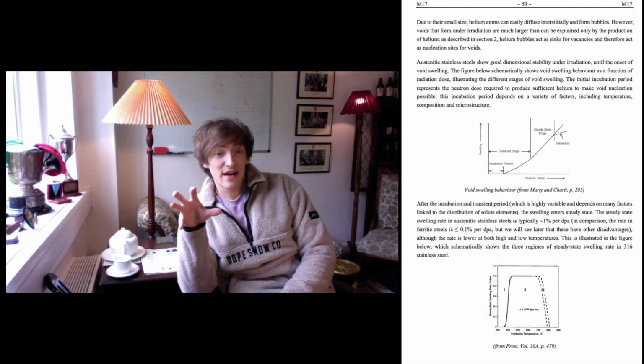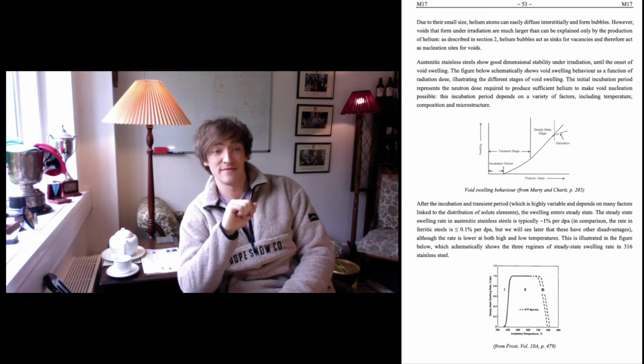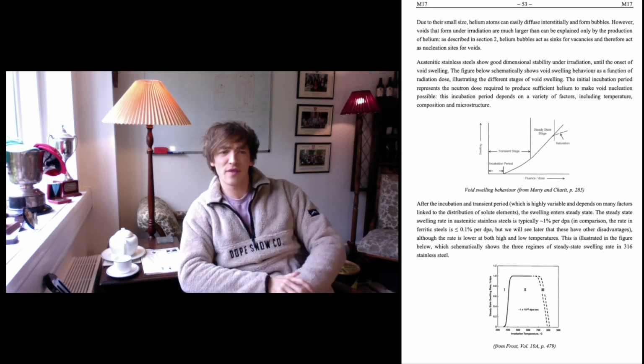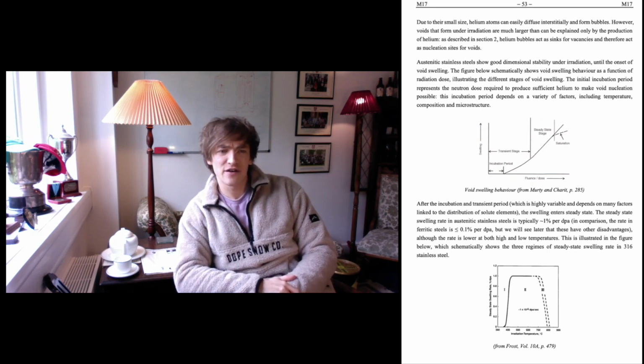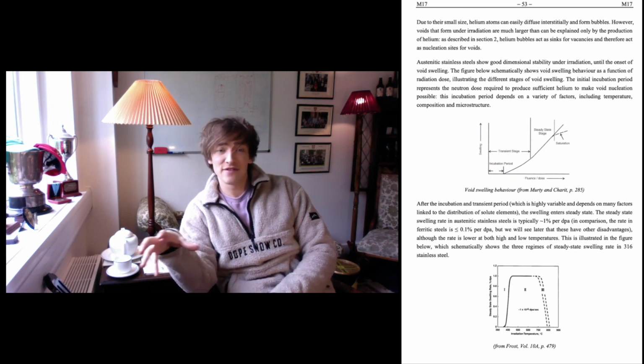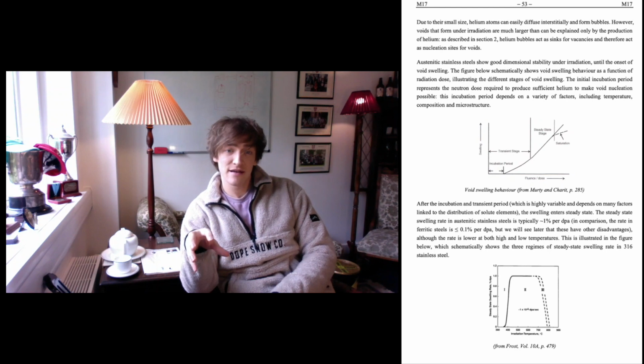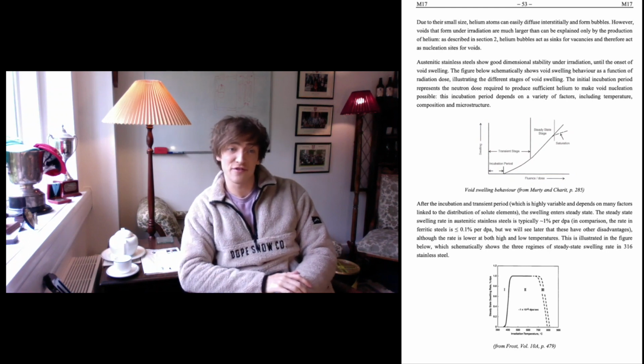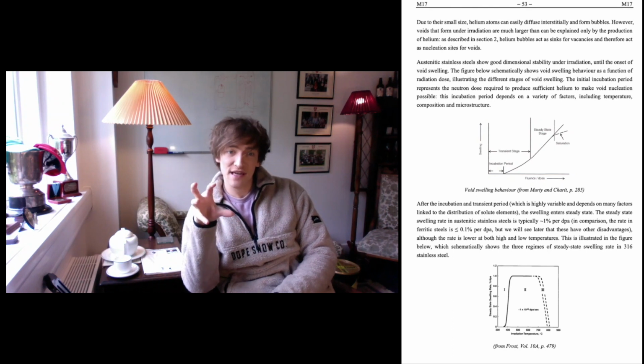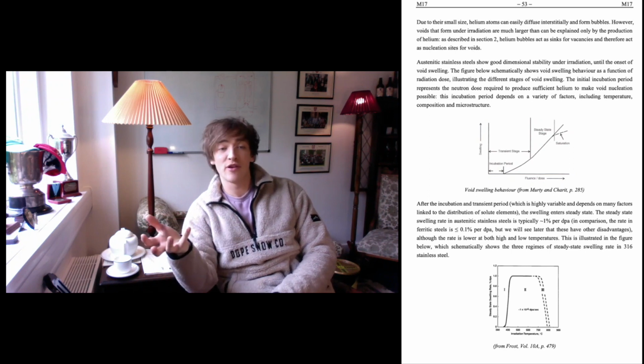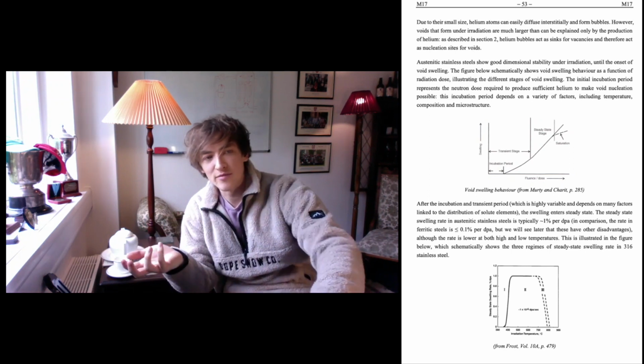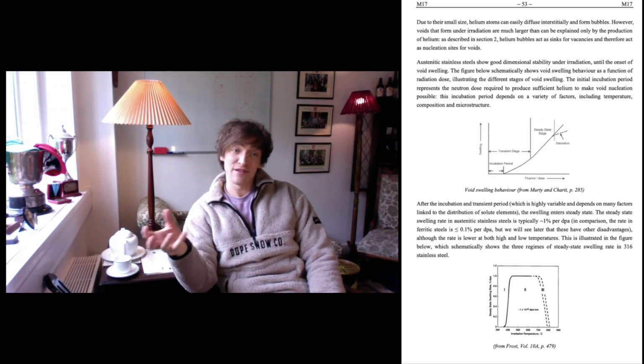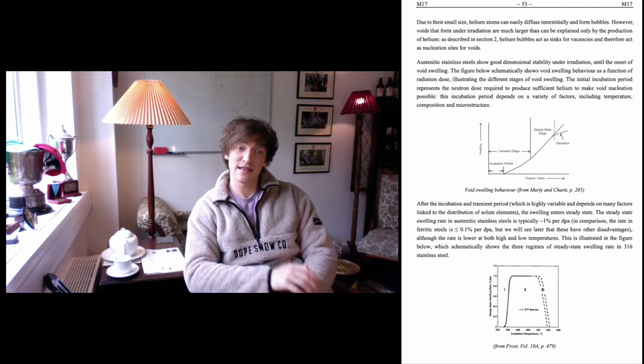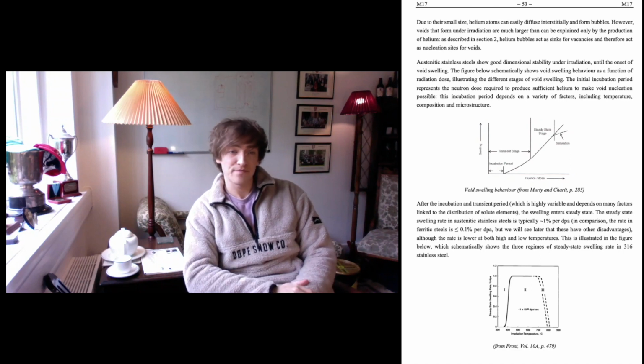Now, austenitic stainless steels have good dimensional stability under irradiation until the onset of void swelling. So the figure at the top there shows void swelling behavior as a function of radiation dose, indicating the different stages. So you have initially the incubation period I just mentioned, which is the neutron dose required to produce sufficient helium to make void nucleation possible. And that's going to depend on a number of factors like temperature, alloy composition, and the microstructure, because obviously you've got different nucleation sites. It's going to affect how quickly these bubbles, or voids, grow.